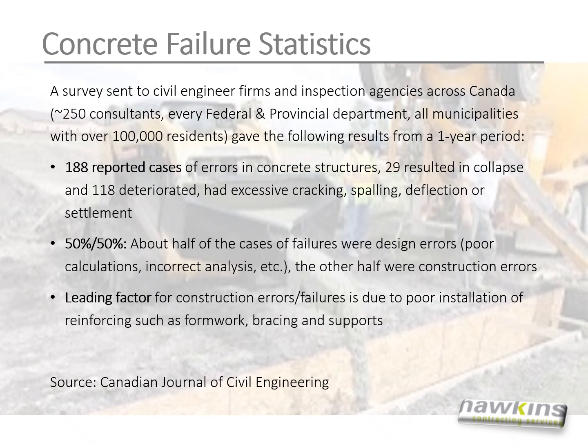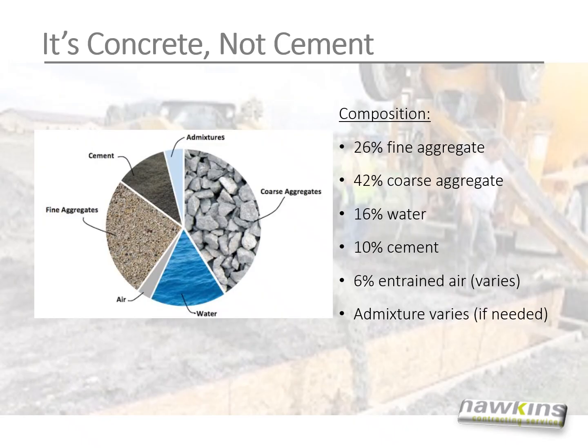Concrete failure statistics. A survey sent to civil engineer firms and inspection agencies across Canada, 250 consultants, every federal and provincial department, all municipalities with over 100,000 residents, gave the following results from a 1-year period. 188 reported cases of errors in concrete structures, 29 resulted in collapse, and 118 deteriorated, had excess cracking, spalling, deflection, or settlement. About half of the cases of failures were design errors, poor calculations, or incorrect analysis. The other half were construction errors. The leading factor for construction errors and failures is poor installation of reinforcing, such as formwork, bracing, and supports.